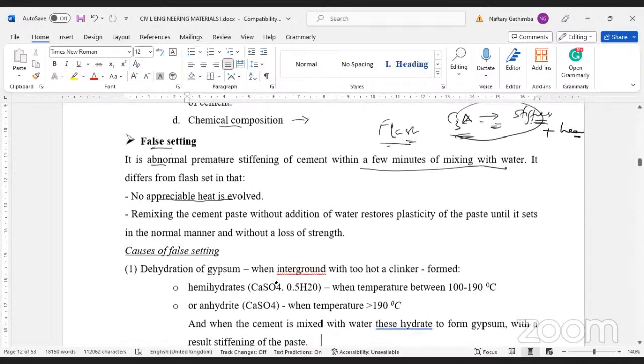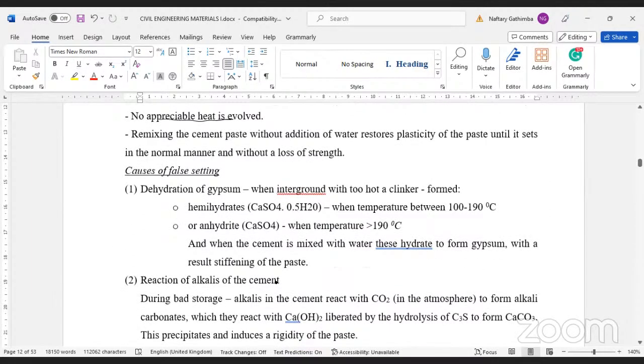So what will cause this false setting? Remember we said flash setting will be caused by an inadequate amount of gypsum. That was one of the reasons, if you can recall, okay? That's why we add gypsum to prevent flash setting. So for false setting, the gypsum may be there, but the gypsum is dehydrated. Remember, gypsum is hydrated calcium sulfate. Okay?